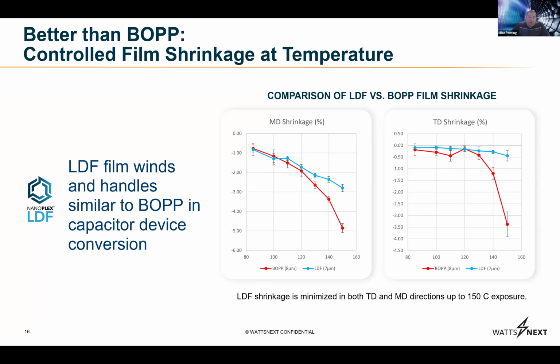Which is really cool for making an ornament. It's not so great if you wind it into a capacitor film and then have to charge and discharge it, and then you have the material smashing down on itself and breaking your device. So you need certain stability, not just survivability at temperature of the polymer materials. We don't want the material just to not degrade. We need it to also not dimensionally change too much that it would hurt the capacitor functionality. So that's something we've looked at in capacitor devices, and this is film data that shows that. Again, the blue lines here are our LDF nanoplex material. The red lines are commercial BOPP material. We perform similar or even a little bit better in terms of dimensional stability at these higher temperatures than BOPP.